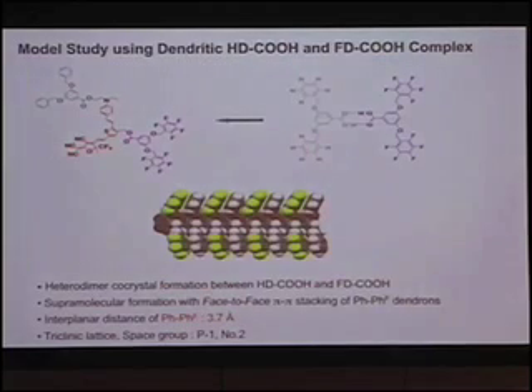If I can increase the number of those rings, the interactive forces you can tap into are not trivial. So basically, we did a model study by taking a nonlinear optical chromophore and building a diphenyl and a fluorobenzene-substituted type of dendron, and another one is a diphenyl dendron. And when we made the model compound, indeed, they co-crystallize in an alternating manner, with an interplanar spacing of benzene and fluorobenzene of about 3.7 angstrom. So this shows you they can indeed form a relatively tight pack.